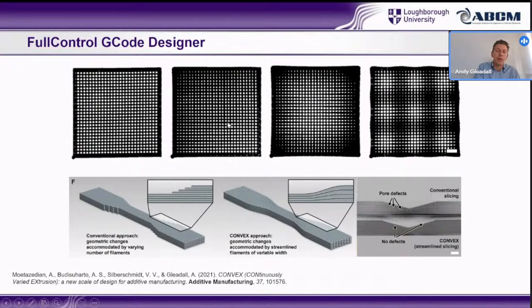And you can either achieve that, if the material is quite responsive, by just telling it to extrude more or less material. Or if it's not a very responsive material, so some hydrogels won't be, or concrete, you wouldn't want to change the flow rate. But you can then change the nozzle speed so that if it's spending less time somewhere, it will deposit less material. And that's what we did here. And on the right, you can see this really graded, nice structure, purely because we've varied the extrusion width.